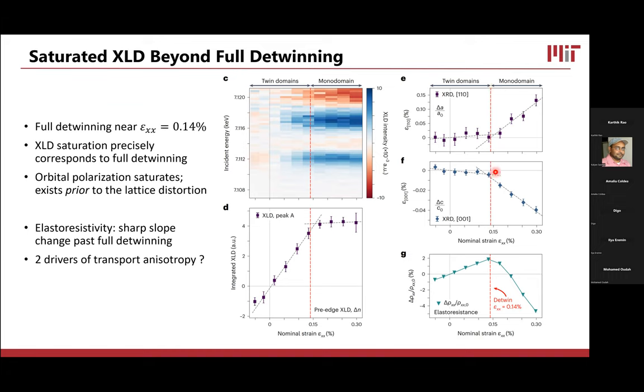Past this point, marked by the red line, we see that the lattice constants shoot off in the direction that they're supposed to. So increasing tension makes the strain-aligned lattice constant bigger, and it makes the out-of-plane lattice constant smaller. Both of these lattice constants show this change in behavior at the same strain value, which is marked by this red line. This red line from the lattice constants defines the red line that's now marked here on the XLD. And we see that it's past this point that the XLD saturates. So this right here is the key indicator that's the heart of the paper, which is that the orbital polarization is saturating once the sample is fully detwinned.